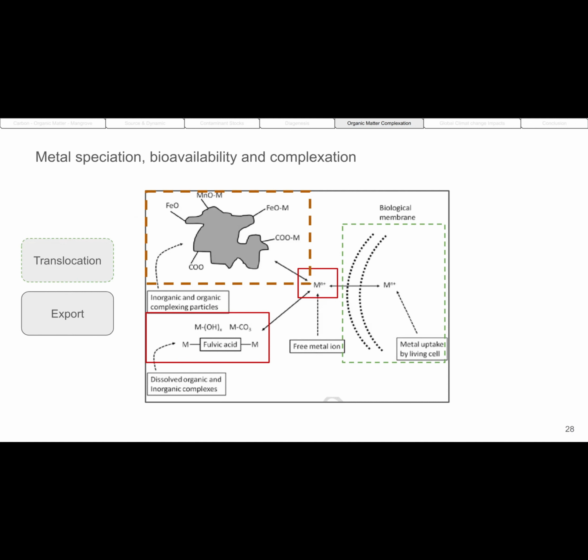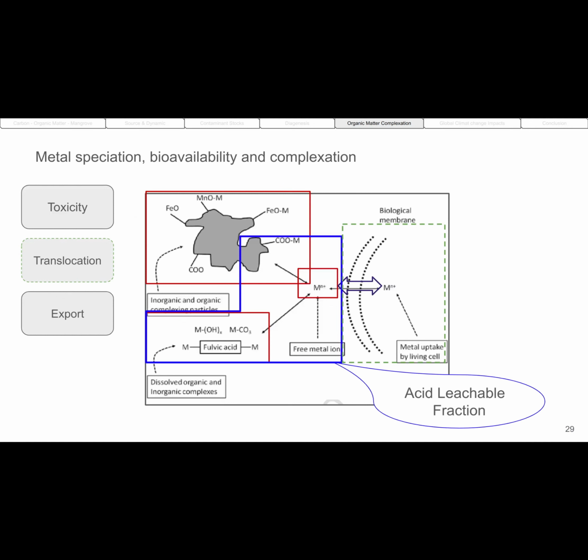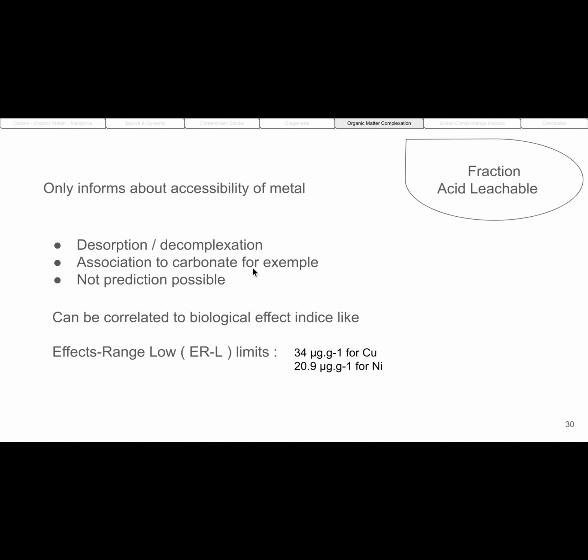How can we measure these several compartments? It's very hard, in fact. The most used is the acid leachable fraction, and this way of measuring the metals in sediments takes into account the free ions, the complex ions, and one part of the metals adsorbed on solids. These methods have some drawbacks. The advantage is that it's easy and rapid, but the drawback is that you cause some desorption or decomplexation by using this extraction. Mostly you have some destruction of the carbonates, and it's difficult to predict what happens if you change the conditions.